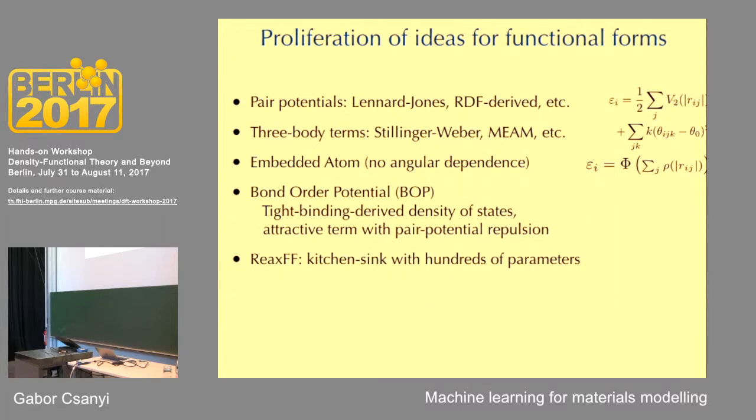It doesn't work for many covalently bonded materials like carbon, silicon, more sp bonded materials. So people have invented other things, adding angle terms, for example. Here's a spring constant k, here's theta ijk, the angle between every triplet of atoms, and that theta 0 is the angle that the material is trying to achieve at 0 temperature, let's say 109 degrees, the tetrahedral bonding. And so you add a penalty for deviations from that, and that's an approximation of the total energy. Not a very good one.